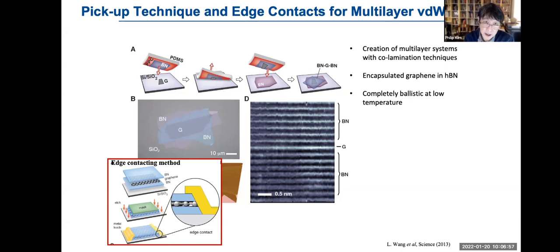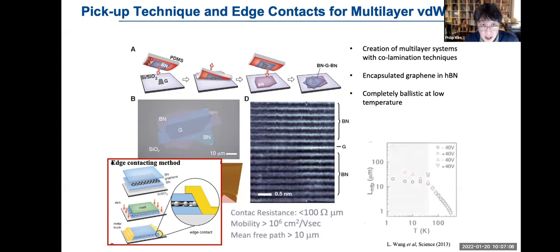In this particular example, graphene in between boron nitride is a good example where the community has developed a way to make selective contact onto the graphene layer and quickly make a device out of graphene. The quality of such a two-dimensional system that you can realize in graphene has improved over the period. Now the mobility, or the mean free path of the electron, in graphene encapsulated in boron nitride easily exceeds several hundreds of microns, as long as it's at low temperature.